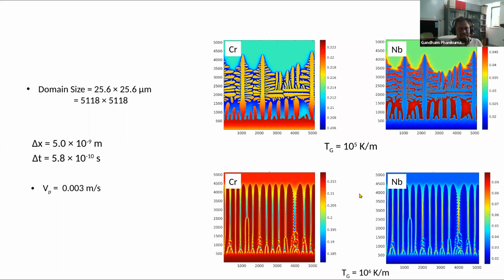So think of it like this. If you have a preheat for the powder bed, the temperature gradient can be reduced. If you do not have a preheat, then the temperature gradient is high. So you can think of this microstructural difference as what happens when you have preheat and what happens when you don't. The temperature gradient actually makes a big difference to the microstructural evolution. You can make out that at lower gradients you have dendrite formation, whereas at higher gradients you have only cellular formation.